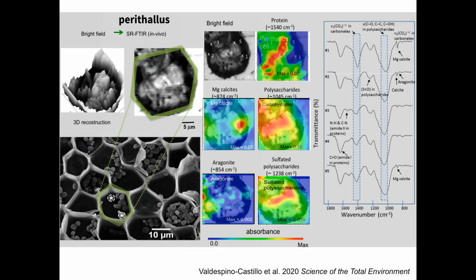And by studying the polysaccharide signals in more detail, we were able to identify an area of some tens of microns rich in sulfated polysaccharides. We were really surprised because we were hoping to detect a starch, that is the material that has been broadly described in the literature as the content of the algal cells. But instead, we found these sulfated polysaccharides, which have also been reported in red algae and are related to antimicrobial defense, but also to biomineralization.